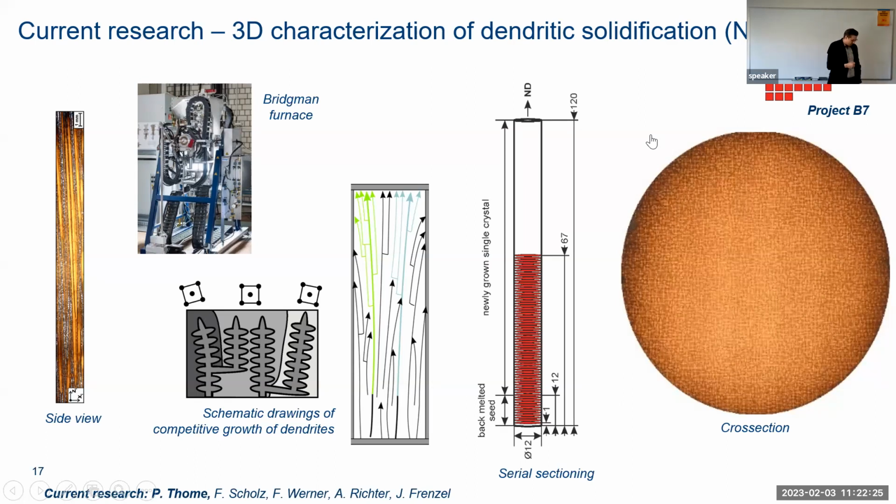And what's happening then is that the crystals that we are producing are not pure, right? There are crystal defects being introduced during the solidification. And one of these crystal defects is called crystal mosaicity. So in an ideal world, maybe I should mention that the solidification happens by the formation of dendrites, because there are chemical segregations happening, but this would be too much.